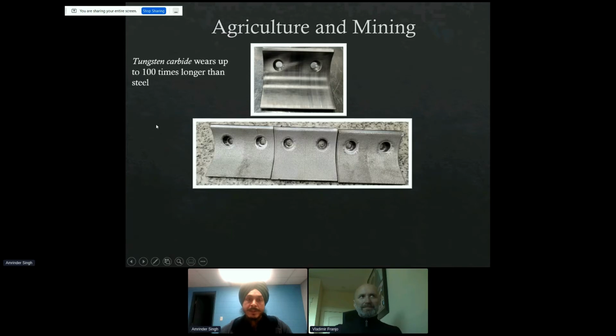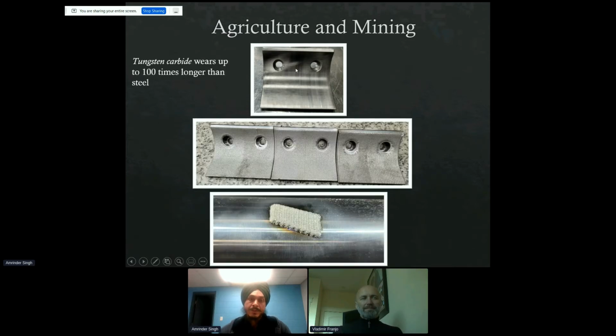From agriculture, we had this agriculture part. This is the shape of it, and we put tungsten carbide onto it using DED. The tungsten carbide wears up to 100 times longer than steel. So this part now has 100 times more life than it had before.